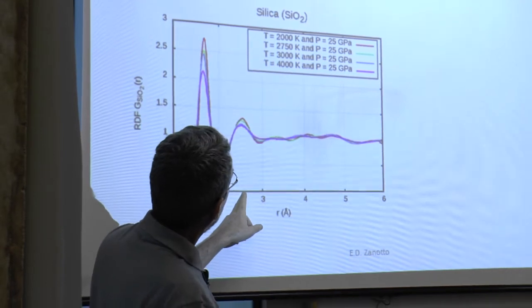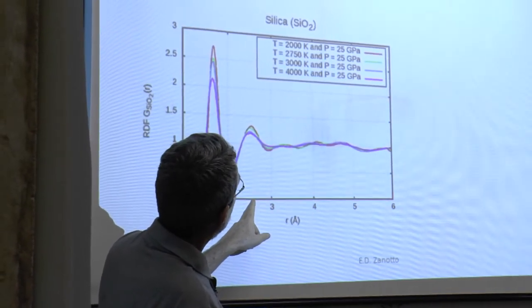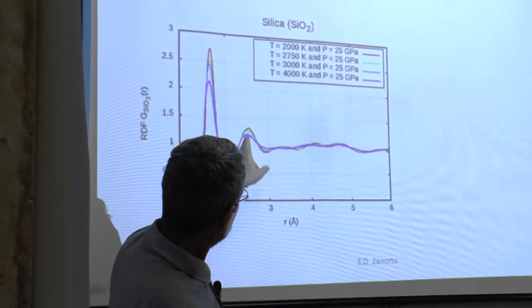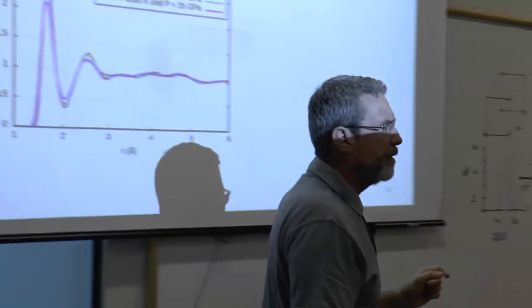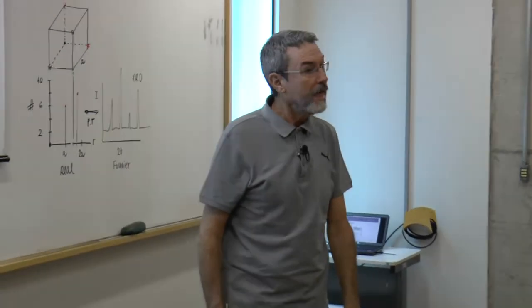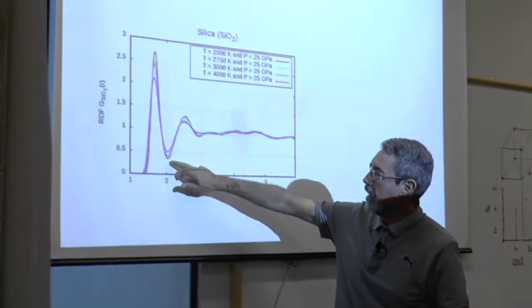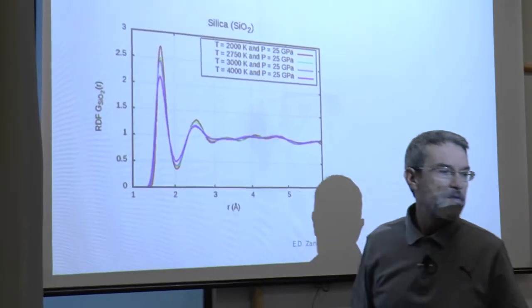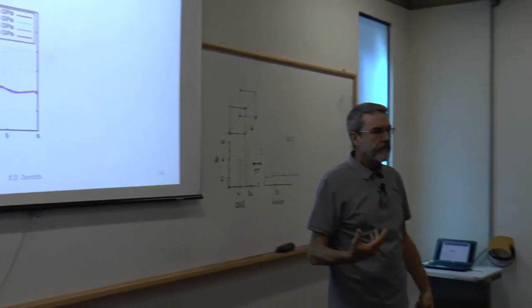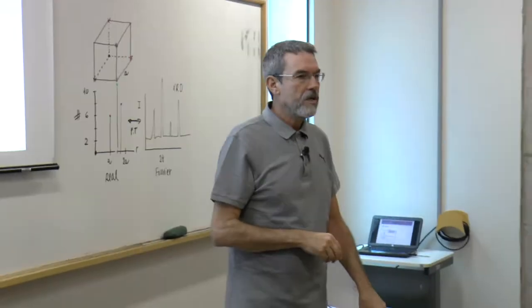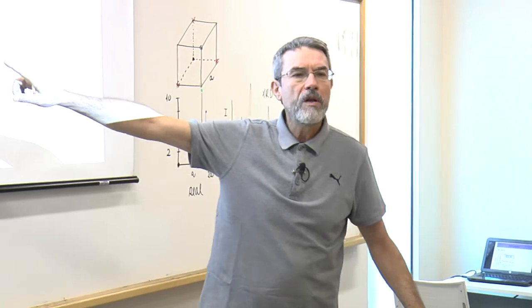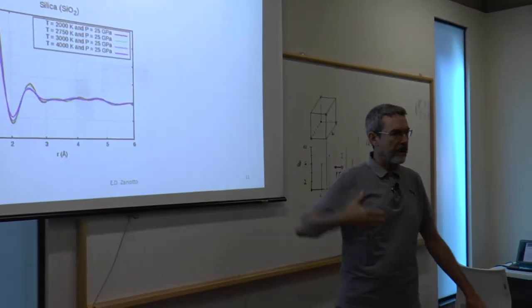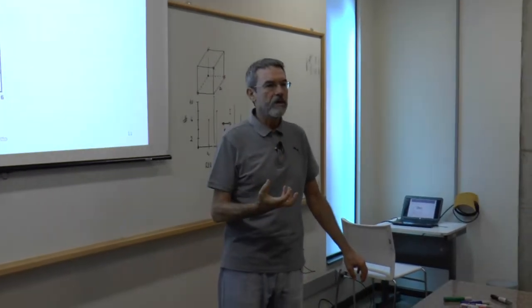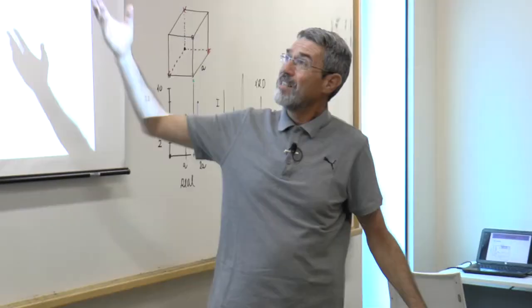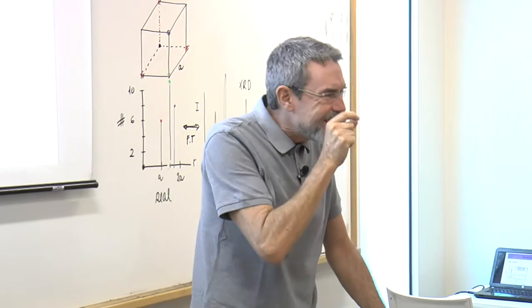And this peak refers to the oxygen distances. 2.5 angstroms or so is the oxygen distance in this SiO4 tetrahedra in the crystal. The areas under these curves give the coordination number, which are exactly the same as in the crystal phase. So for glasses, I'm giving only one example, but there are many examples in the literature. There's a whole community that works on glass structure. So the structure of glasses, silicate glasses in this case, at short range order is exactly the same as the structure of their isochemical crystals.